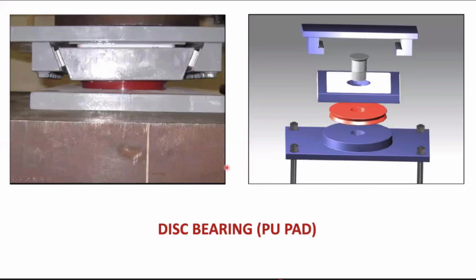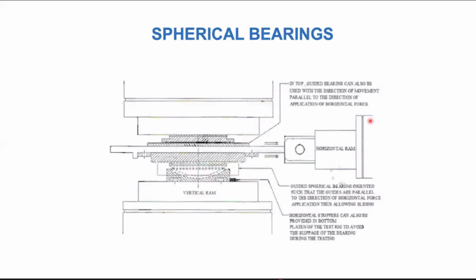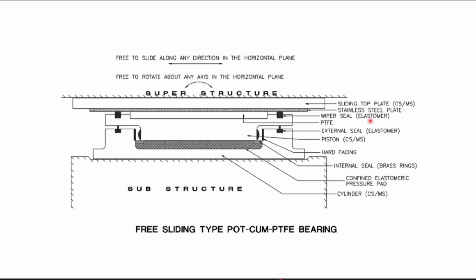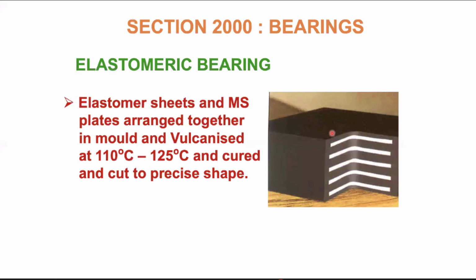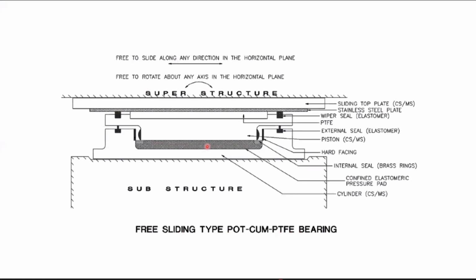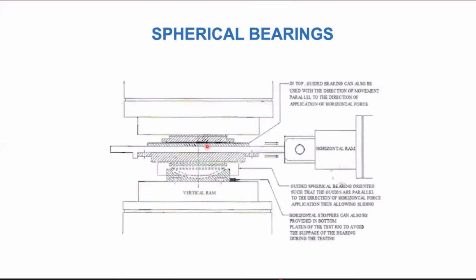From Sandfield. There is another type of bearing, that is the disc bearing. These bearings were used first time in India for the Worli Bandra sea link in Mumbai. In this bearing, you have a disc of a material called polyurethane, which is a very high capacity material. For larger loads, this bearing is suitable because it requires a lesser area to transfer the load, as it has a high capacity. In fact, if you go up and see here, an elastomeric bearing will take a pressure of about 10 MPa. A pot bearing will take a pressure of about 25 to 30 MPa. And a spherical bearing will take a pressure of about 30 to 45, 50 MPa.